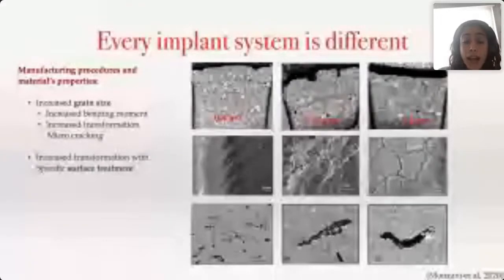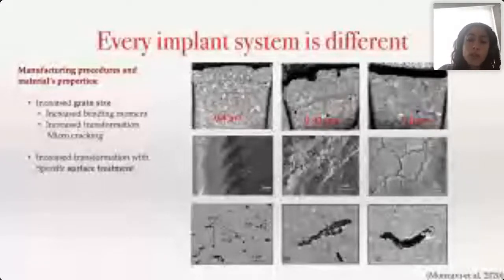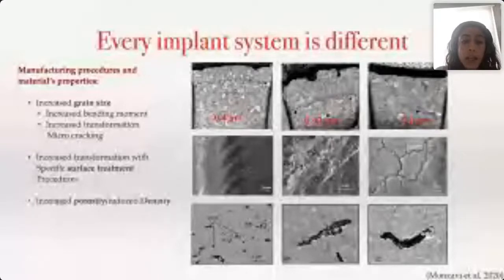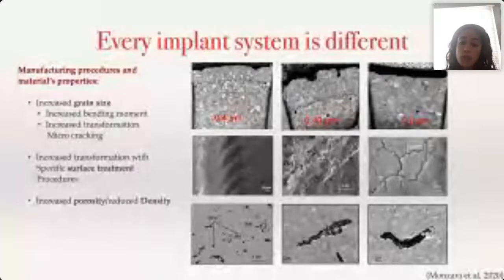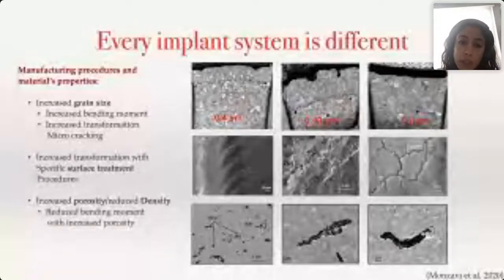Also, they affect the implants through different surface treatments. All these implants have different surface treatment, and if there is too much roughening or surface treatment, that may also affect the material's properties. Most importantly, it's important to avoid porosities inside the material, because that can lead to reduced fracture toughness of the material.